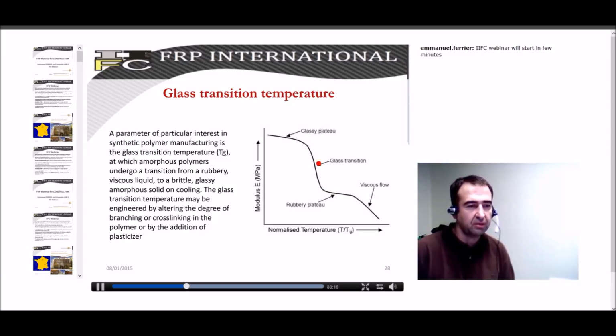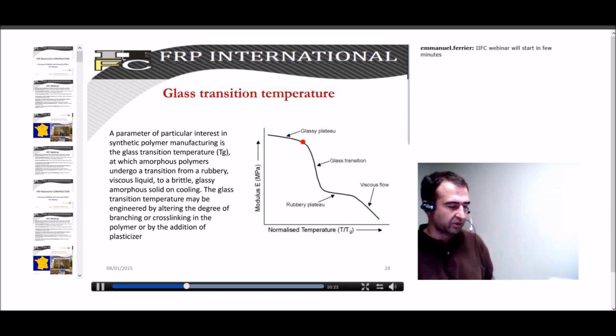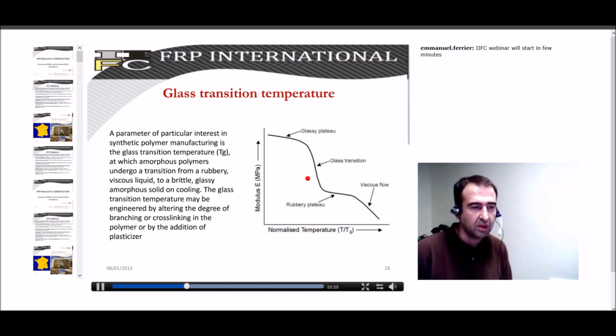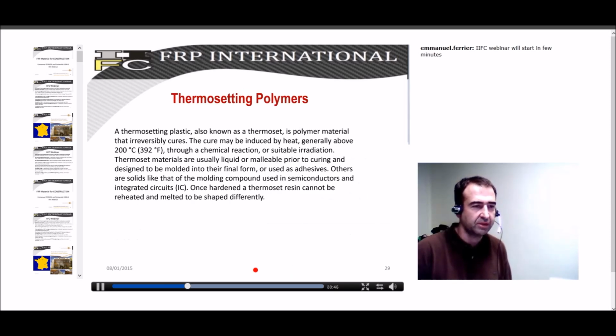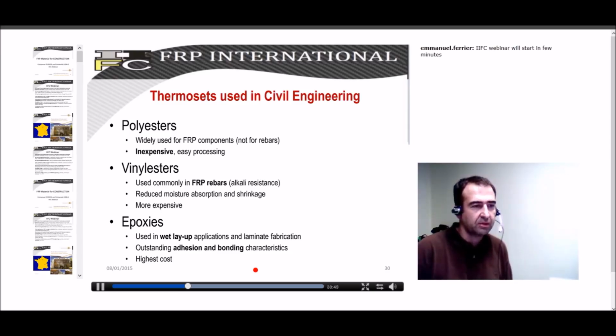And this may be compared to the material used, for example, to build a road. It's a material coming from the petroleum industry, and it behaves in different ways depending on the temperature. So we identify a value which is the glass transition temperature of the polymer, corresponding to the value where the mechanical properties decrease. A common thermoset polymer used in our industry is epoxy, used for wet layup applications of laminates and dry fibers.